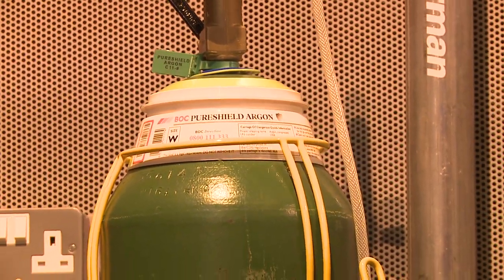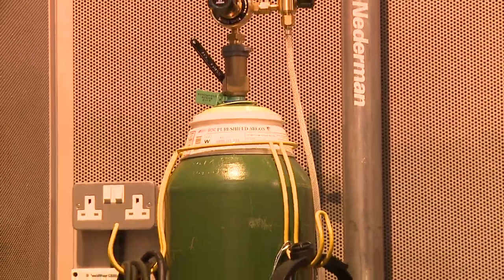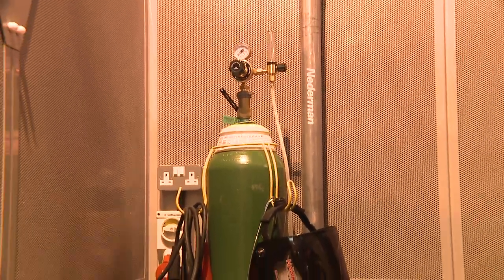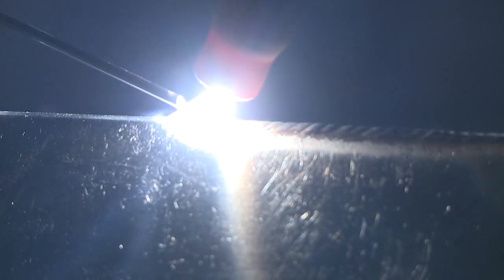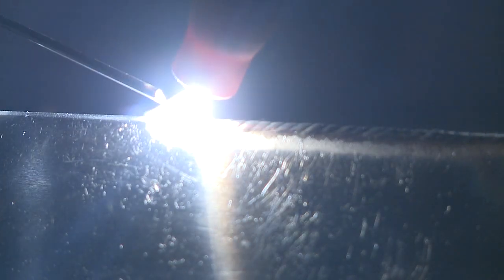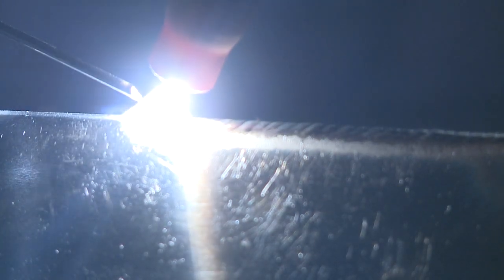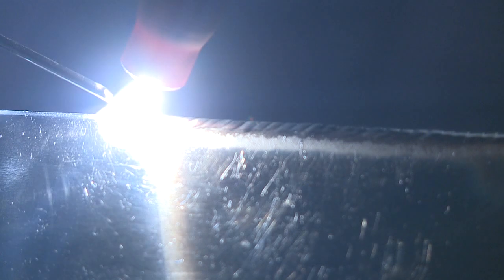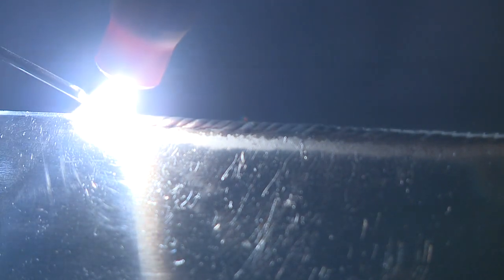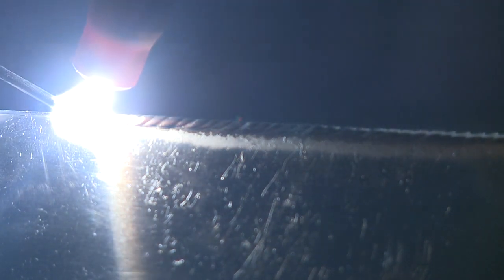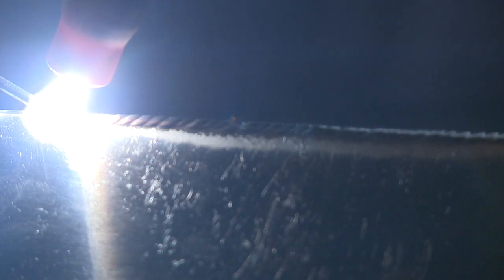Argon is colourless and it has an ionising potential of around 15.7 volts. Argon has a low thermal conductivity, which results in a more compact, high density arc. The energy is more concentrated and is therefore confined to a narrow area. It has excellent arc stability and cleaning action at low amperages.